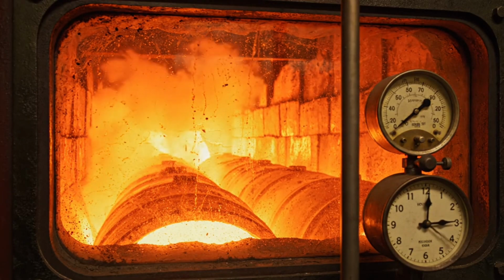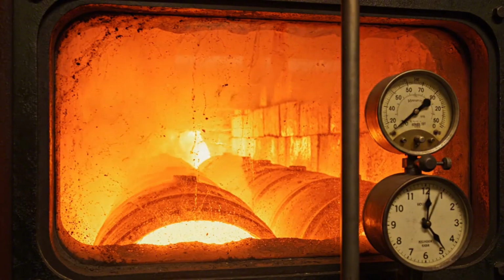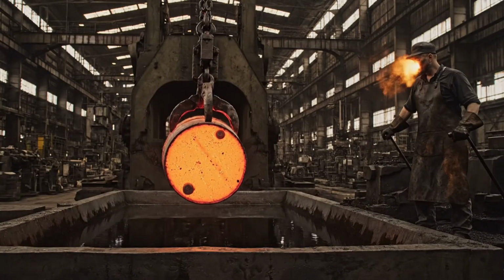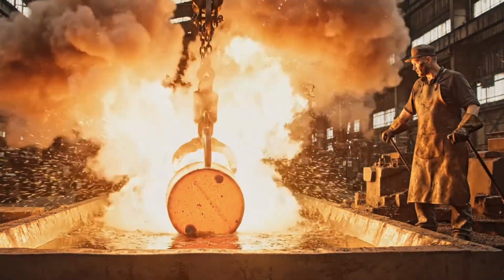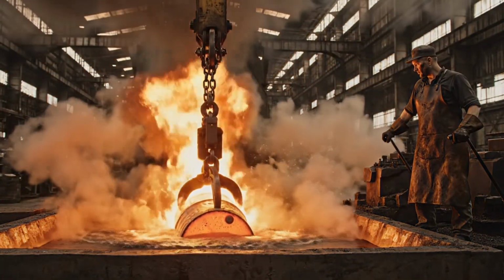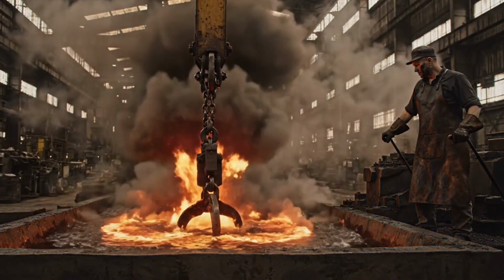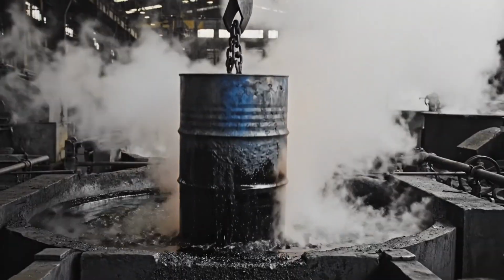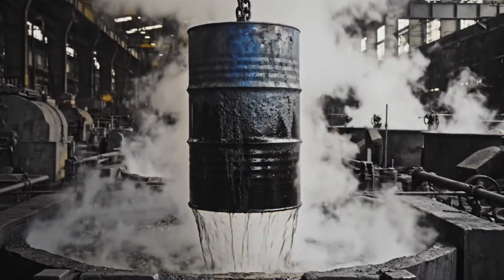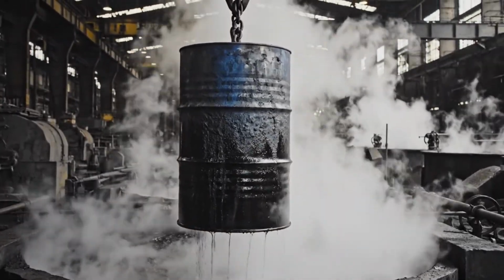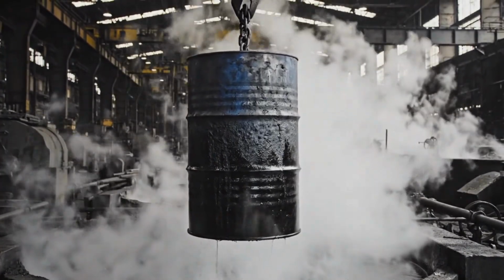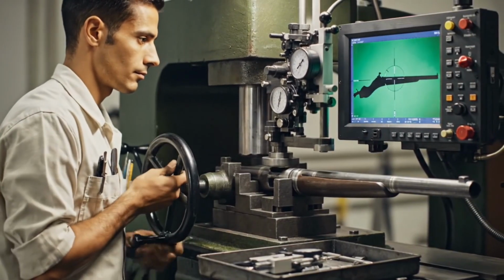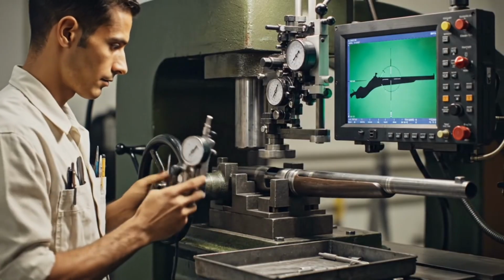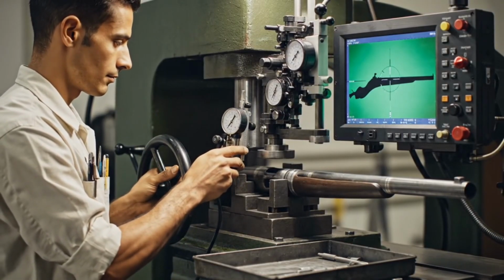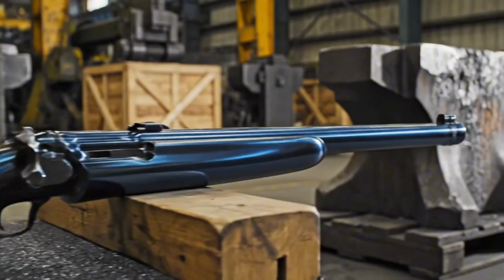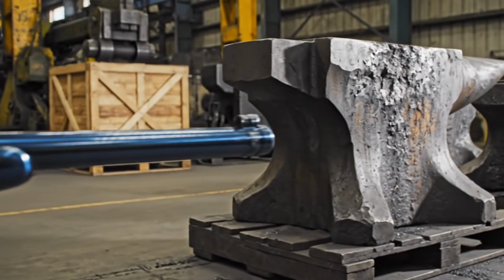They were heated to 1,550 degrees Fahrenheit in electric furnaces, held at that temperature for precisely timed intervals, and then quenched in oil baths that cooled them rapidly. The sudden temperature change transformed the steel's crystalline structure, making it harder and more wear-resistant. But heat treating also introduced warping, so every barrel had to be straightened on hydraulic presses, while machinists checked them against optical comparators that could detect deviations measured in 10,000ths of an inch.